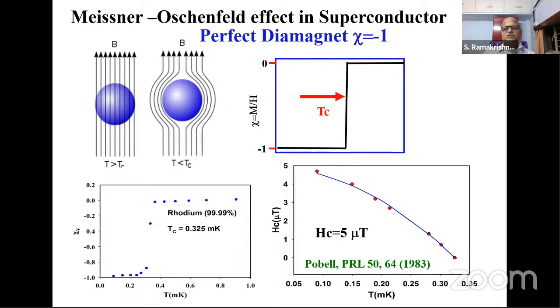So how do we test our system, whether it works? You take the lowest superconducting transition temperature element like rhodium, which was done more than 30 years ago. We took that rhodium and showed that it is indeed a superconductor at 325 microkelvin, slightly less than what they have reported, because there is probably a much purer sample than ours. The important thing is that you measure its critical field as a function of temperature. That matches with this paper, which was a landmark paper on the superconductivity of rhodium. Which means that our magnetometer works.